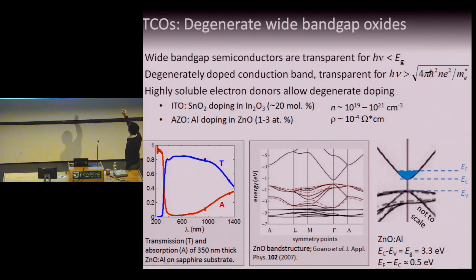This is represented by this equation here, where hν, the frequency of the light, is smaller than the band gap, E sub g. For zinc oxide, which is the material I've been working with, this band gap is in the undoped state between 3.3 and 3.4 electron volts. Amazingly, there's still some debate over that. But that's going to make this material transparent for our eyes. So you can see through windows and you can see football.